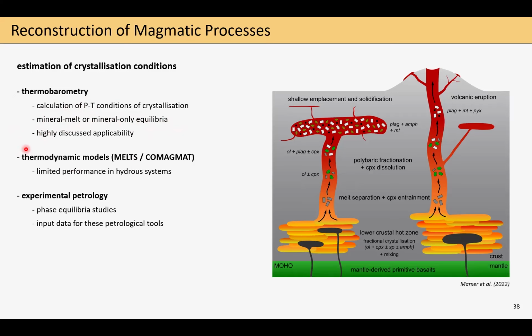Alternatively, we can also try to simulate the crystallization of a melt using some thermodynamic models, such as MELTS or Comagmat. However, also these are currently showing quite a limited performance in water-bearing systems, so for example, calc-alkaline magmas. And another thing we can do is run some experiments, for example, running some phase equilibrium studies, trying to simulate or reproduce some natural observations, where these experiments can also serve as crucial input data to further improve the two previously mentioned petrological tools.